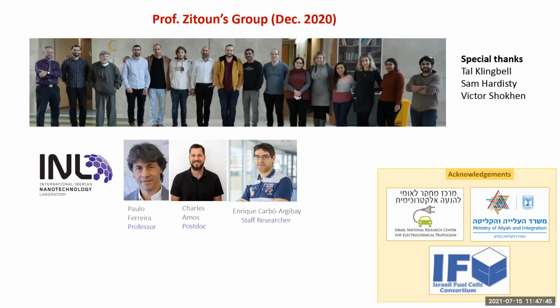Yeah, that's what I asked. Yes, also the opposite. Sometimes we are so concentrated looking for exactly perfect shape and a perfect distribution, but we found that particles that are less homogeneous and less pretty by design have even better performance. But if we don't do the first characterization in the lab, and if we don't analyze the degradation, and if there are thousands of particles that are created and only few reach the fuel cell, usually you have one good candidate among a lot of them. So it will be very difficult to test everything. Understand. So you just do the initial testing in your lab.